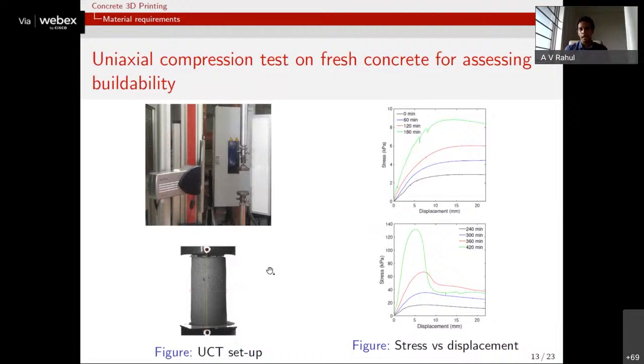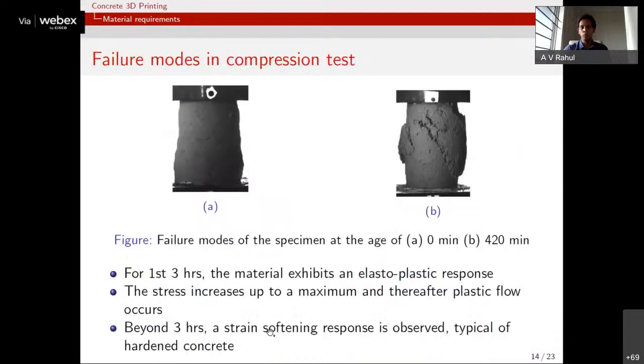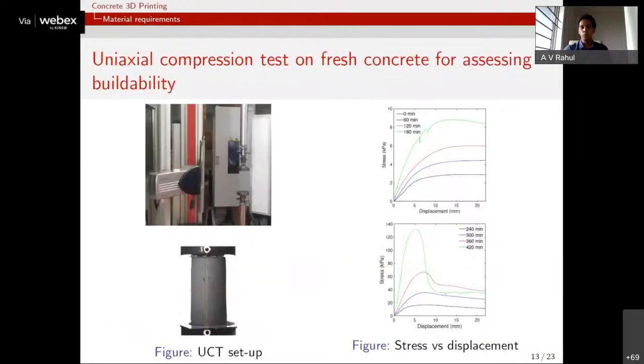Because there's a high yield stress for this early age concrete, 3D printable concrete is stiffer than conventional concrete. Even when you demold it, it can still retain its shape. Then we do this test with a very sensitive, very low capacity load cell, and we capture deformation using a video extensometer system. In fact, you can do this test at different time intervals. Here you can see that the maximum value is increasing as the time interval proceeds, and you can also see it from 240 to 420 minutes.